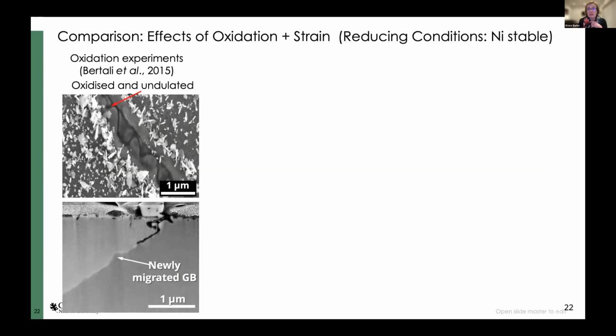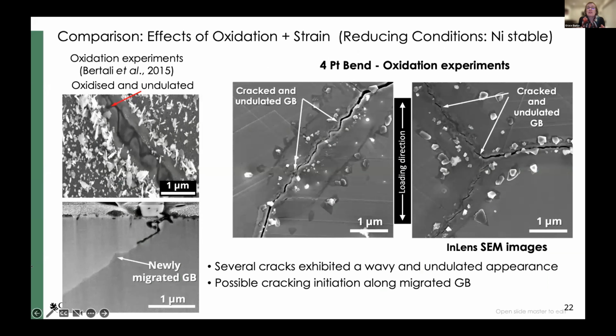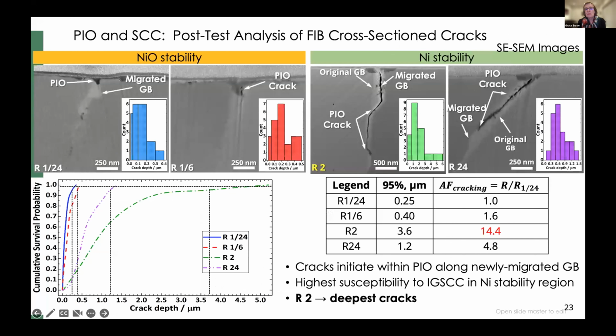So here's with unstressed, and here is what happens when it's stressed. We do see that we have a lot of cracked, undulating grain boundaries here. Possible crack initiation along the migrated grain boundaries? Well, we must do a lot of work, many grain boundaries to assess that. And those data are presented here, but what I want to point out to you is while there's very small amounts of preferential intergranular oxidation under oxidizing conditions, under reducing conditions, we get some significant cracking down the boundaries, particularly when we're close to this magic nickel-nickel oxide transition.